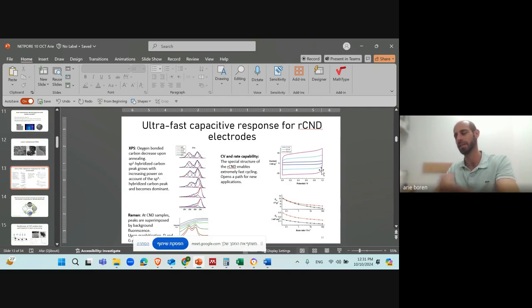And we could cycle the supercapacitor very fast. It is actually, if you see it, 10 volts per second. It is considered to be very high. It is maybe 100 times faster than conventional activated carbon that we have in commercial supercapacitors, and we'll talk about it later on. Okay, so this is a very good result that is made only because of the special structure that could be achieved by using the smallest building blocks, the carbon nanodots.